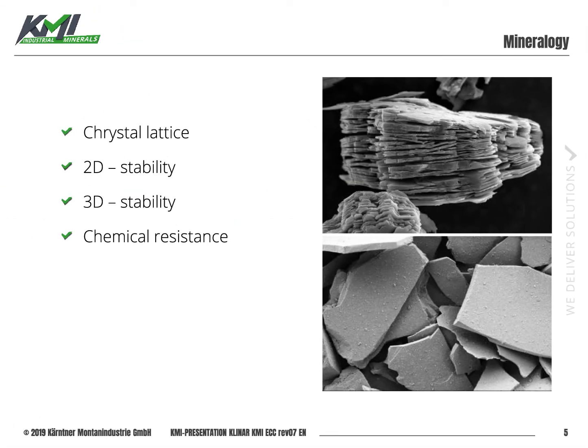When you look at the mineral itself, not only the shape is important, also the crystal lattice is important. For example, if you compare a mica particle with a MIO particle, there's a big difference. When you look at the mica particle, it's only a two-dimensional stable crystal lattice. That means you have strong bondings within the layer but weak van der Waals bondings in between the layers.